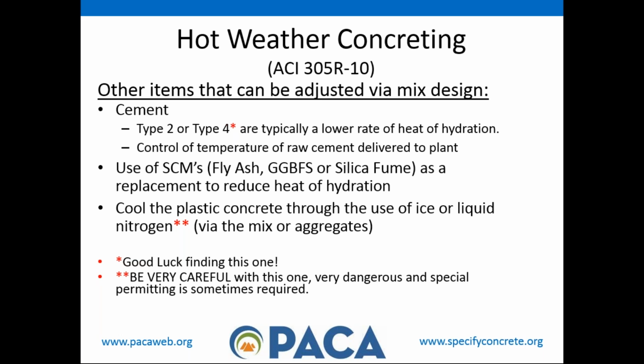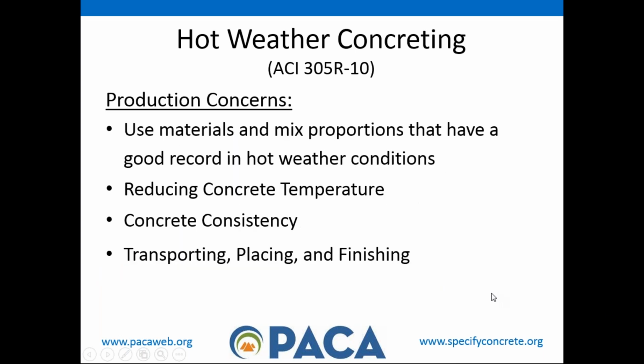Okay. So, obviously that's a derivative of the heat of your mix, the cement. Obviously, getting extra warm cement from the mill causes an issue. If there's any way you can set tankers aside, let them cool down, that helps. The use of SCM, supplementary cementitious materials, fly ash, slag cement, fume, they all help. And obviously cooling the concrete down, everybody's favorite is use of ice. Liquid nitrogen is one thing that can be used, but I would strongly, strongly caution people, if you've never used it, get somebody who has to work with you, because it is very dangerous. You can cause life-threatening injuries with it if it's not handled properly.